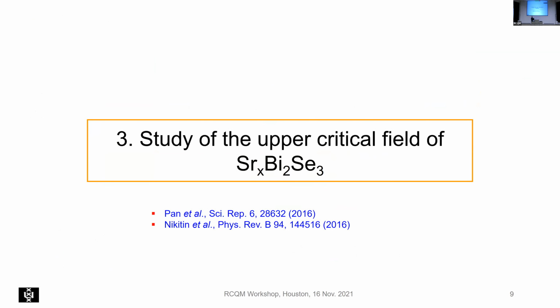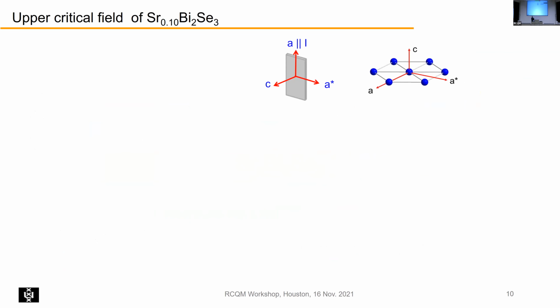So now I come to the study of the upper critical field. And actually, it's a fairly simple experiment. We just have a slab, a flat sample. The z-axis is perpendicular to the sample surface. We put the current along the a-axis, and you can also define the A* axis here. That is the axis which is at right angles to A and C in the plane. But normally you're only interested in a field direction along the z-axis and a direction in the plane.